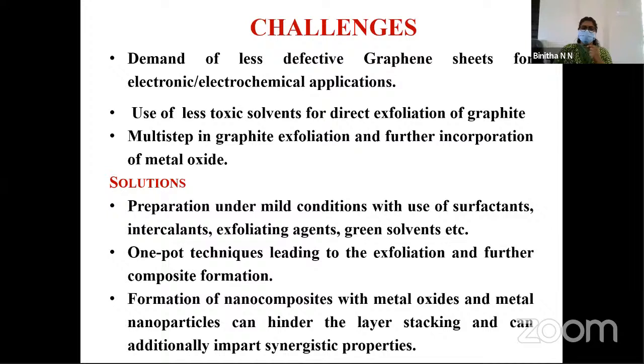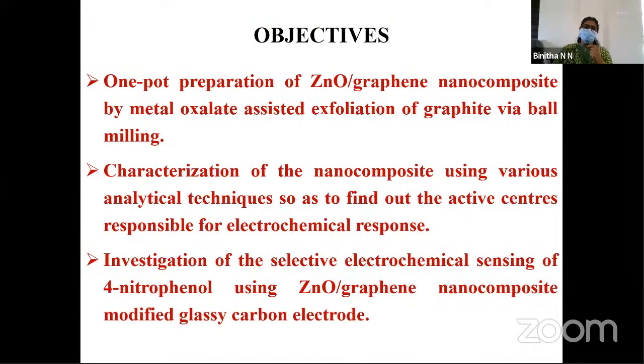In addition to improving the properties of individual components, the metal oxides or any other component can prevent the layer restacking of graphene back to graphite. So the present objectives are one-pot preparation of zinc oxide graphene nanocomposite, and the preparation is done via metal oxalate assisted exfoliation of graphite via ball milling. The prepared material is characterized to investigate its properties, to check whether it is feasible for electrochemical response, and we applied it for the selective electrochemical sensing of 4-nitrophenol.